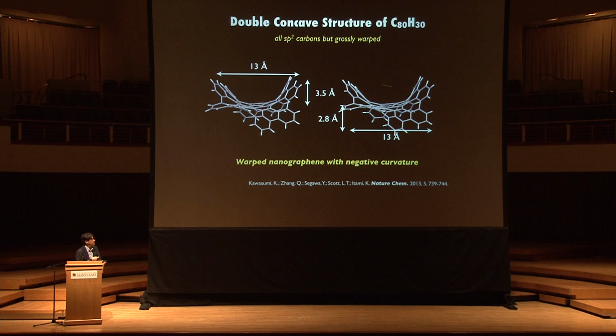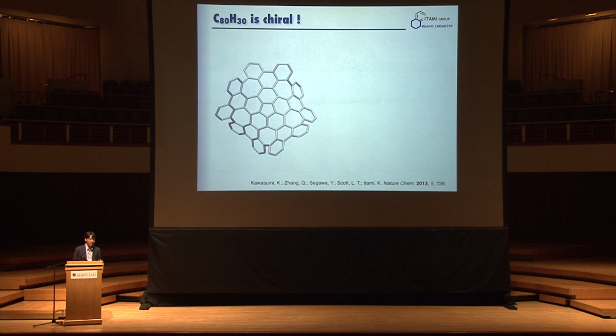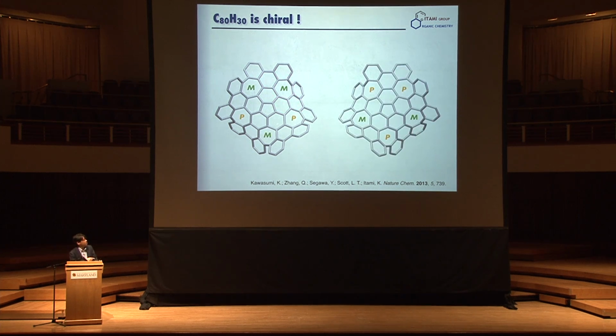Most importantly, this has a saddle-like negative curvature, which is important for having three-dimensional nanocarbons. So we named this the warped nanographene. Let me tell you a little bit more about the structure. It turns out that this warped nanographene is chiral. If you see this part, you can see it as a helicity, so you have an M and P helicity. The most stable structure that I found in X-ray is MPMPM. Obviously, you have an enantiomer here.